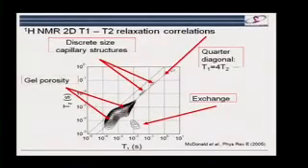So when you've got free water, you have a very long relaxation time because the water is moving around, it never hits the edges. As you go to smaller and smaller pores, so we're going to smaller and smaller pores down here, we have shorter and shorter relaxation time. And this experiment, where we've got two different relaxation times, T1 and T2, and I'm not going to worry about the details of this.